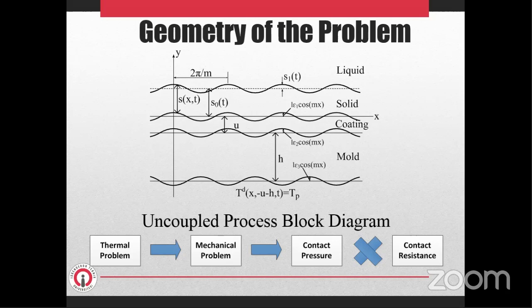As mentioned in the previous slide, the thermal and mechanical problems must be investigated together. This figure shows the block diagram of the uncoupled solidification process. It can be seen from the figure that the thermal problem affects the mechanical problem, but the mechanical problem does not affect the thermal problem in the uncoupled model. This means that the temperature distributions in the solid layer affect the thermal stresses, thermal distortion, and contact pressure, but not vice versa. These temperature fields are not affected by the stress fields.